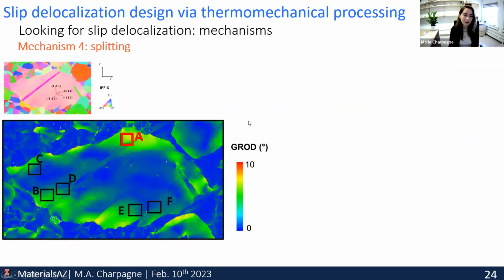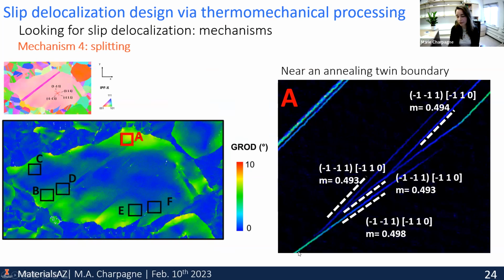And finally, we have an extreme event that's very interesting. We call this splitting, and I want to illustrate this in the central grain of the dataset. This is when we have a slip band that splits into many parts, and we can see that this is a direct result of the lattice rotations. All the split parts still follow the same slip system, but the dislocations are distorted onto that plane that's physically distorted. And we have a breaking apart of the initial slip band into many different parts that have much lower intensity. So we're still quantifying the distribution of those slip bands, but we'll find for sure many more slip bands of lower intensity. And by all four processes, we decrease our overall slip localization distribution.